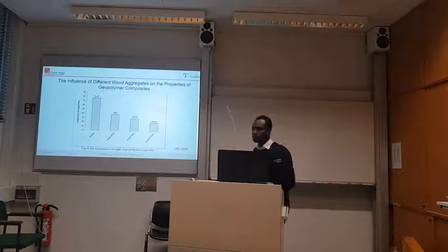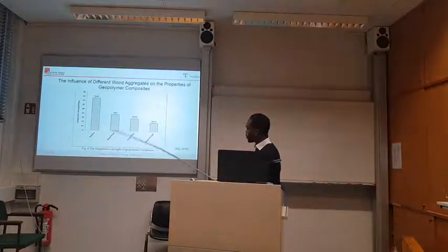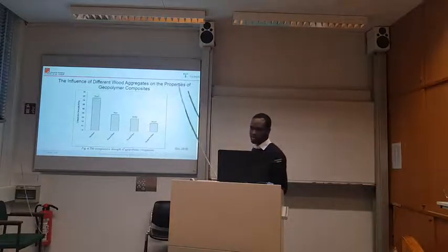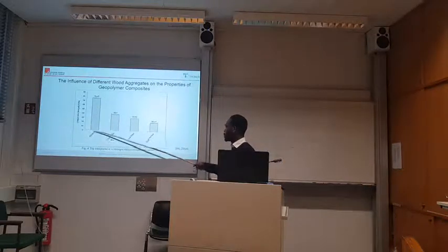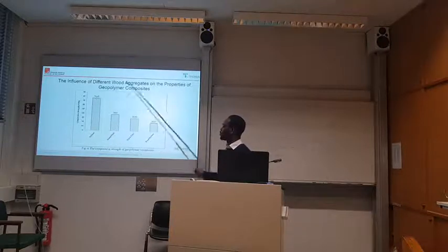And this is also a work from one of the previous students of Andras Kauser. This research also contains, so here what we have is 20% of the wood material in there, but here we have the compression strength, and here we have the pure material without wood, so the strength is somewhere 76 megapascal.